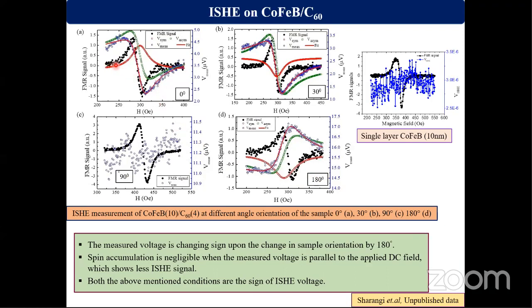So these blue dotted points are the experimental data of the VISHE. And this red one is the fitted line. This ISHE signal has both symmetric and antisymmetric components. We have decomposed the symmetric and the antisymmetric components. Here the red line is the symmetric component, whereas this green line is the antisymmetric component.